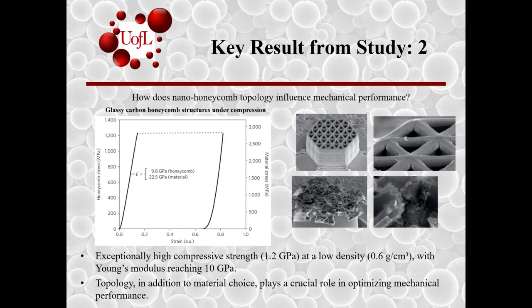The second part of the study looked at how nano honeycomb topology influences mechanical performance. This part of the study examined the impact of honeycomb structures on compressive strength and stiffness. The figure on the left presents the stress-strain curves for honeycomb structure nanolattices, showing that this topology achieves high compressive strengths of 1.2 gigapascals at a density of 0.6 grams per cubic centimeter. With the Young's modulus, it also reached 10 gigapascals. This performance is attributed to the honeycomb's stretching-dominant deformation mode, which efficiently distributes the load and minimizes